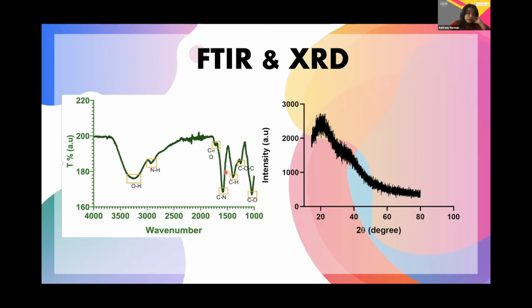An increase in oxygen groups leads to an increase in surface defects. These surface defects allow excitons to be trapped, giving a red-shifted emission during the photoluminescence. The presence of the functional groups also gives rise to very outstanding solubility of the nanoparticles. In the XRD result, around 2 theta of 20 to 21 degrees, it shows a peak, meaning that the structure of the carbon dot is amorphous.